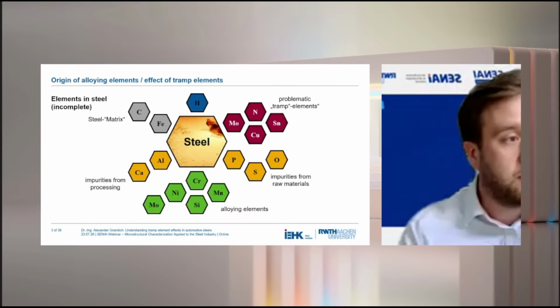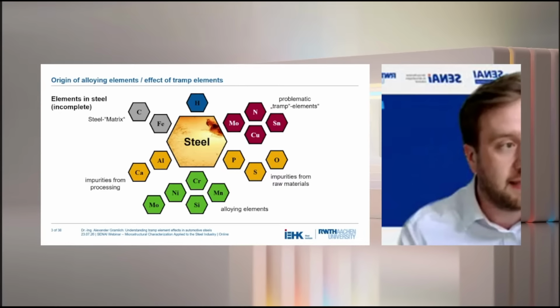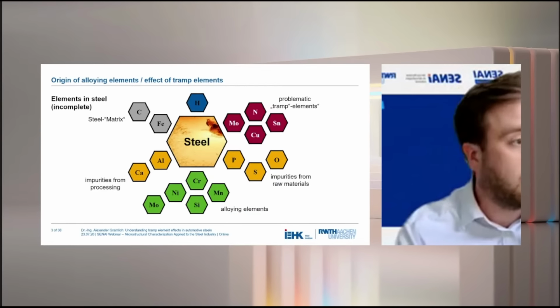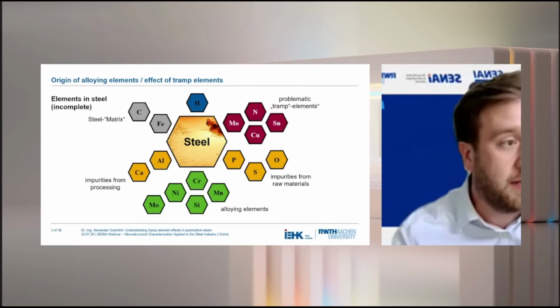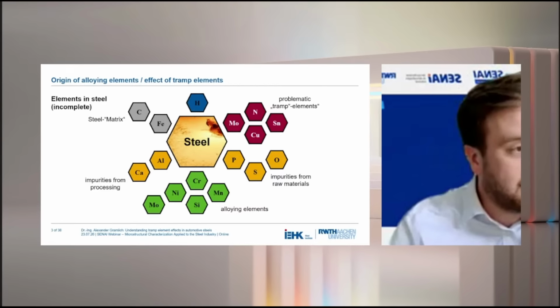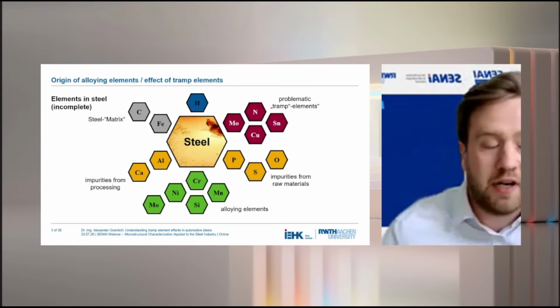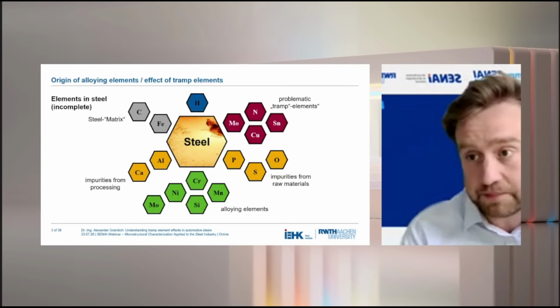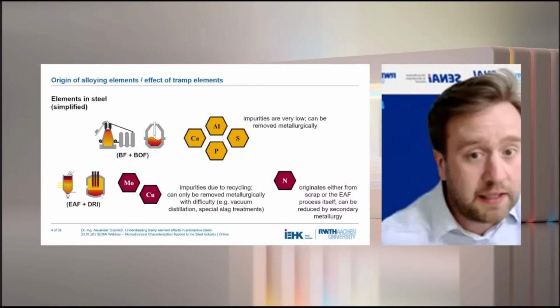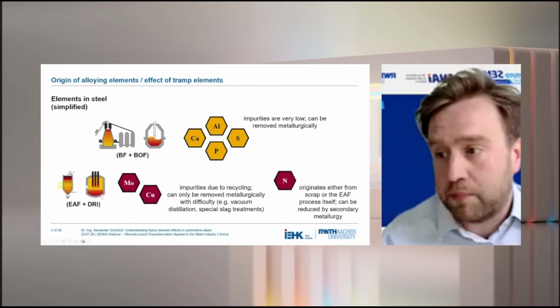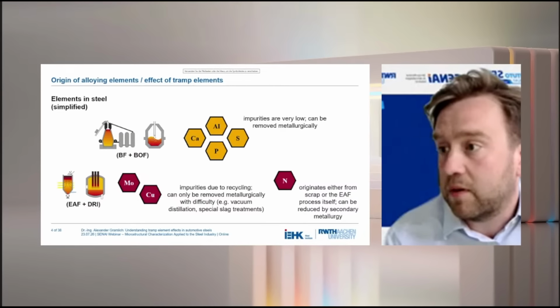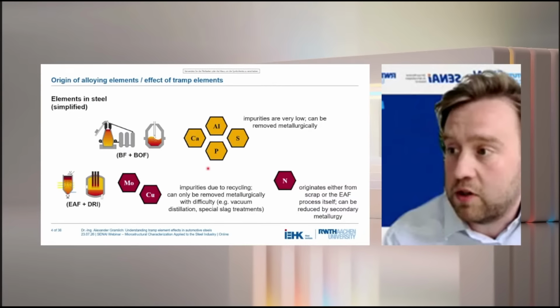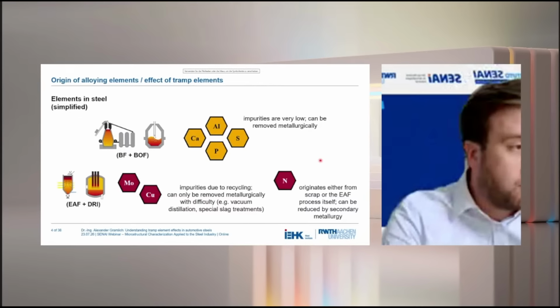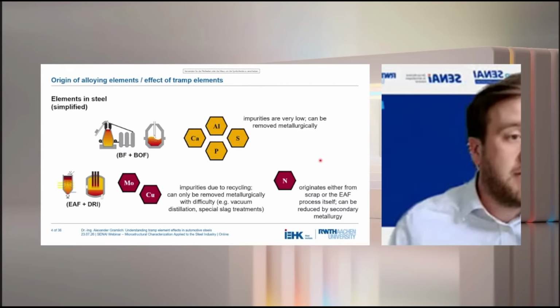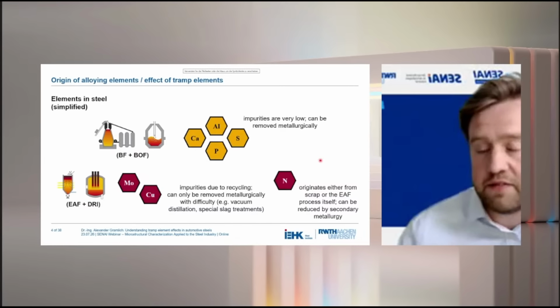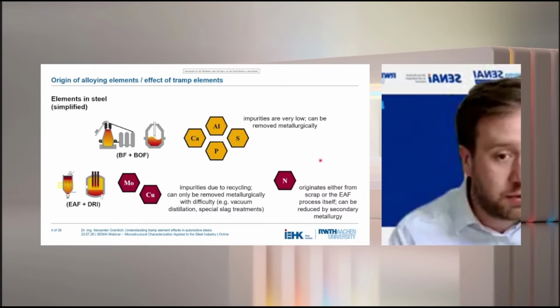So if they are once in your steel cycle, with every recycling step, you will enrich it and get more and more copper, for example. And over time, these copper additions can be really significant and will more or less destroy your steel concept. What's their origin? When we are talking about the primary steel production, we have calcium, aluminium, phosphor, and sulfur, which come from raw materials, for example. They can be, as already said, removed relatively easily by metallurgical approaches.